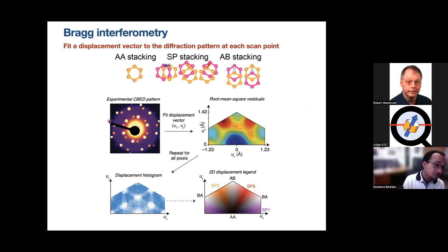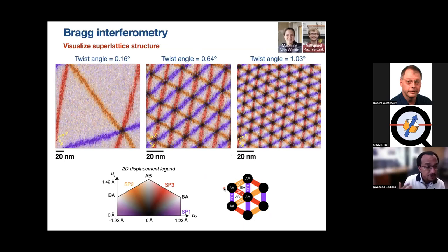What we do is more quantitative, where we take our experimental convergent beam electron diffraction pattern and actually fit a displacement vector to that, minimizing the residuals going with that function I described. And then we can assign each pixel inside this displacement legend, where we encode information about the X and the Y components of that displacement vector. So this is a hue value color scheme, where the hue or color gives you information about the angle of that displacement vector, and then the value, the brightness or darkness, gives you information about the magnitude of that displacement vector. So then we end up with maps that look like this, which are vector valued displacement maps, where the color of each pixel encodes information about the displacement vector at that point.